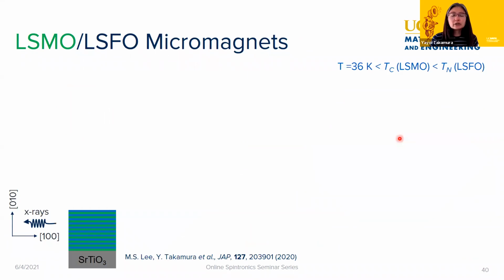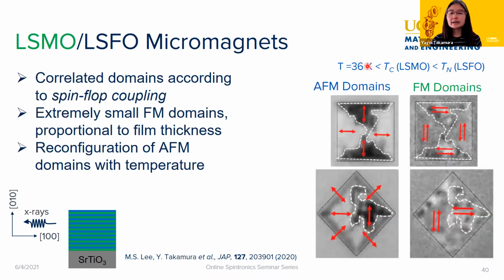And then the last one that I wanted to show is, again, going back to the sample where we had the LSMO micromagnet. Before we were looking at room temperature; we cooled the sample all the way down to 36 Kelvin, which is now below the Curie temperature of the LSMO layer, right? And then we got these kinds of structures. On the right are the ferromagnetic domains, on the left are the antiferromagnetic domains. What we were able to see is that there still is correlation between the ferromagnetic and antiferromagnetic domains, but now because the layers are so thin, the ferromagnetic domains are extremely small.